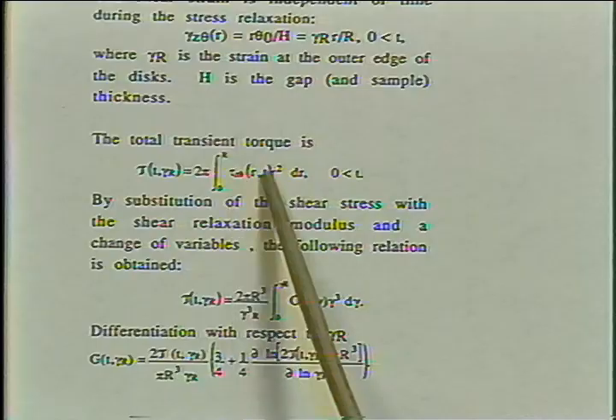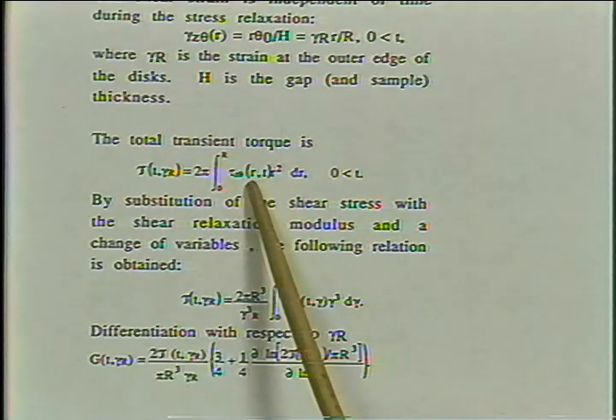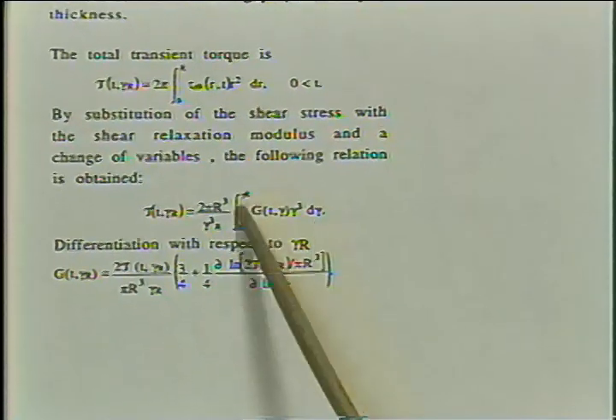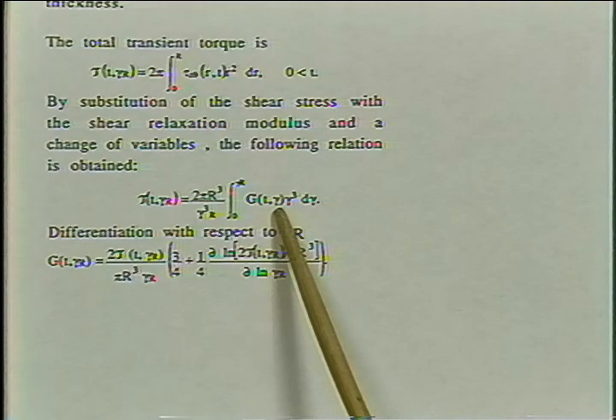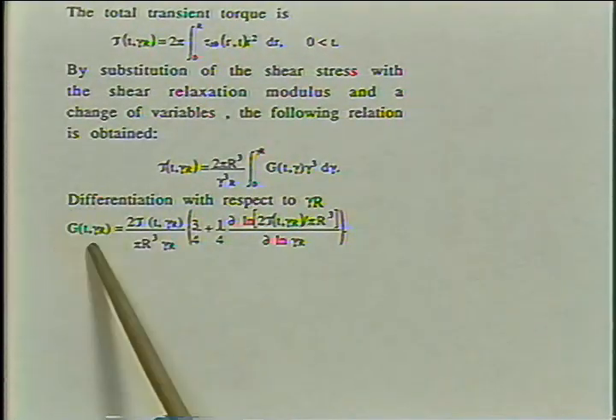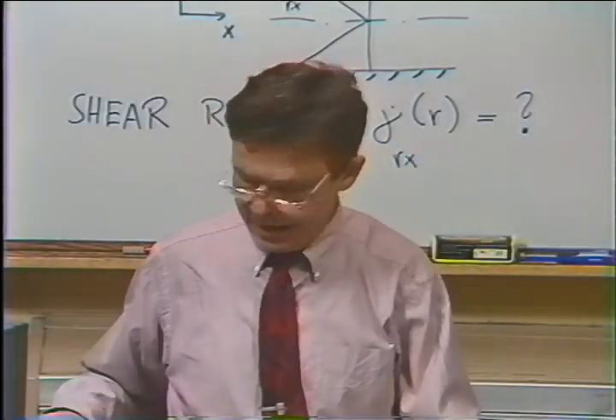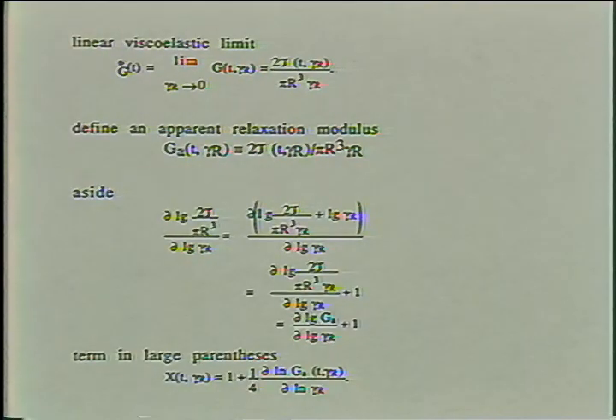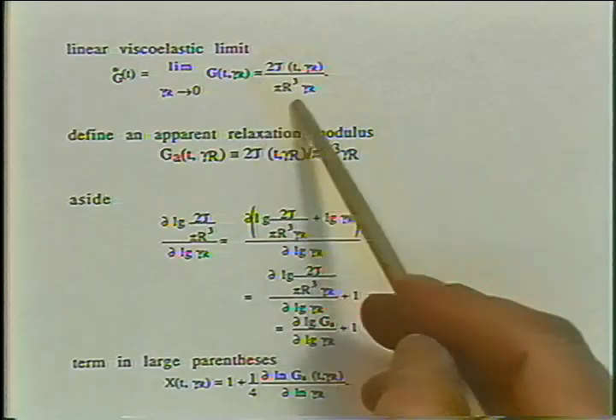The resulting stress is given by the integral of the shear stress, and this integral contains the radius, and the radius can be replaced with the shear strain which we are imposing into that system. So we replace the radial dependence, and we just get the modulus as a function of strain, and you do the same type of integration as Rabinowitsch did, and you find now that the real modulus at some large strain is given by this front factor modified with this term. Now the front factor is all you get if you work with a Newtonian material, with an inelastic material. If you work in the linear viscoelastic limit, you only get the front factor. So you get this here, and we would call this the apparent relaxation modulus.